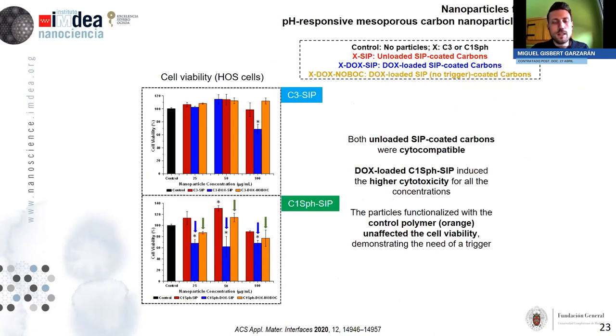Okay, so after that, we carried out a preliminary cytotoxicity experiment using doxorubicin with human osteosarcoma cells. And here we had four different groups. The control is just cells, so no nanoparticles. Then we had nanoparticles functionalized with the polymer, but without drugs. Then nanoparticles with the polymer and with doxorubicin, which is an anti-cancer drug. And finally, nanoparticles with doxorubicin and with a polymer that contained the same structure, but without the pH-responsive moiety. So in theory, we were expecting no release from these nanoparticles.